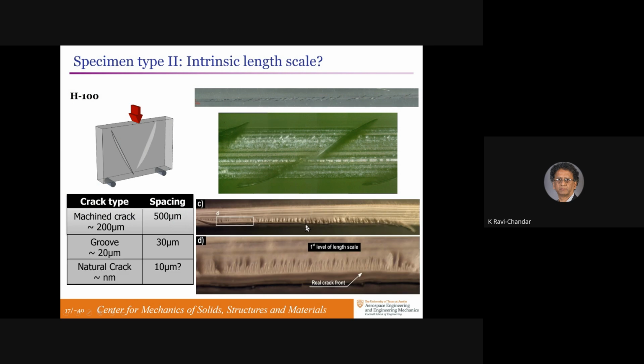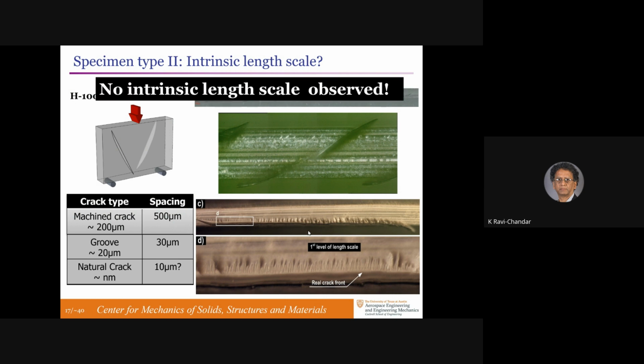there are undulations on the surface that are on the order of tens of microns, and the cracks are on the order of tens of microns spaced from each other. So it's whatever the length scale of the crack front is that dictates the spacing, because it's an elastic unloading over some length when the first crack pops. So there's no intrinsic length scale. The scale is governed by the scale of whatever the defect is that triggers these daughter cracks.